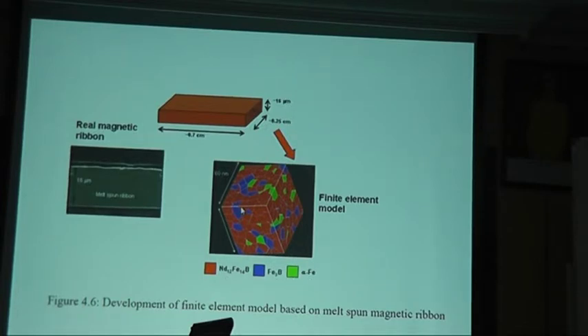There are a lot of models. Some researchers use regular grains, but in this case I use irregular, which is more real, because in experiments we cannot get regular, uniform grains. So we try to make it irregular, similar to the experimental magnet. Because it's melt-spun, the grains are in intimate contact, meaning no intergranular phase, direct contact, no amorphous. This is too ideal, because in a real magnet we of course have a percentage of amorphous, but in the model we consider it completely crystalline, 100%. So this is ideal.